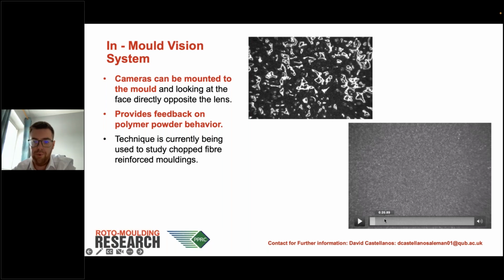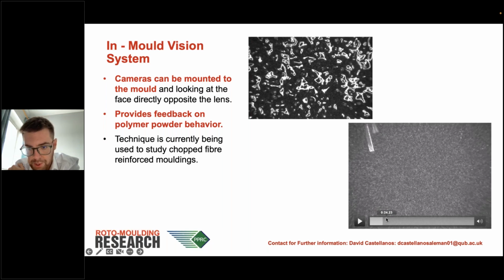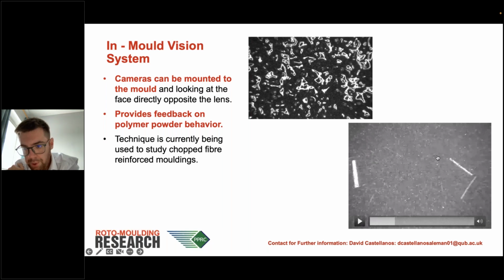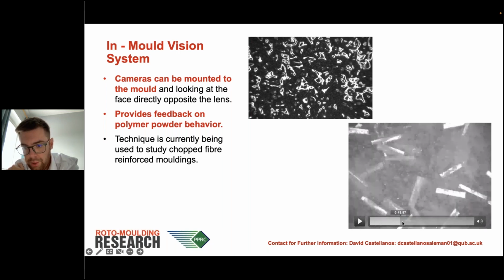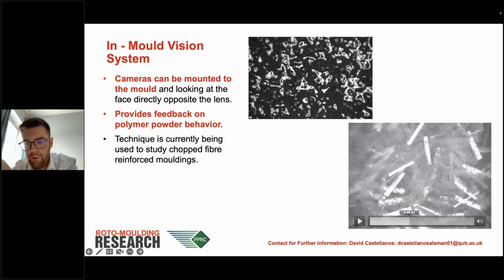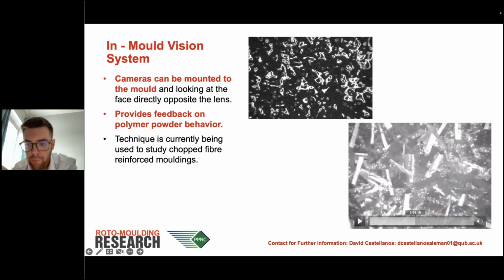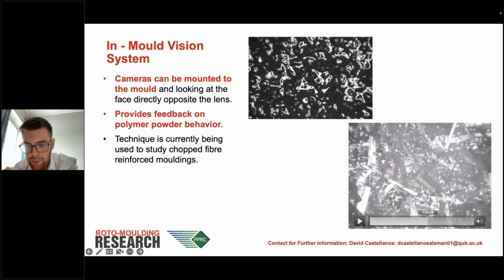So if we take that a step further, and you then put chopped fibers into the same molding, what you start to see is at the early stages, there's fibers sort of passing by the camera but not sticking to the mold because it's not hot enough yet. But at a certain point, layer by layer, the polymer starts to stick to the mold, and you can see that some fibers start to get captured within that polymer melt. And iteratively, then you get a layer after layer buildup of polymer with chopped fiber. So he's been able to use this to identify things like how many fibers were stuck onto that polymer wall, and the orientation and layout of those fibers within the image, which can then go to optimizing things like the robot movement to be able to control where those fibers are placed.